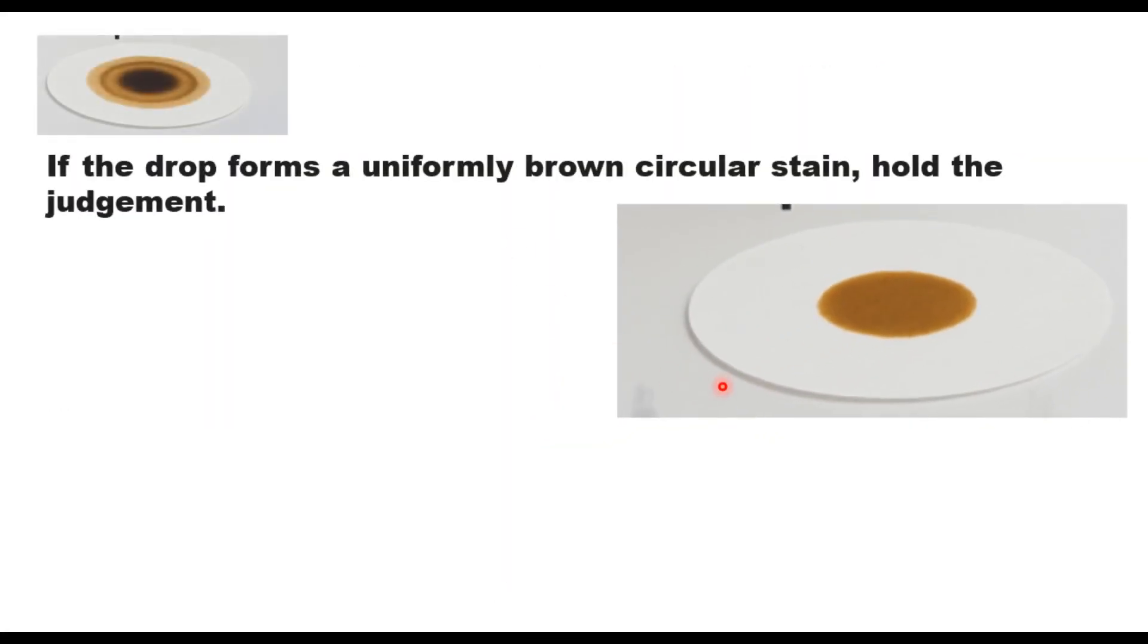But if the drop forms a uniformly brown circular stain, then hold the judgment. It means you do not declare whether the test is positive or negative. Keep the sample for 24 hours and then repeat the test.